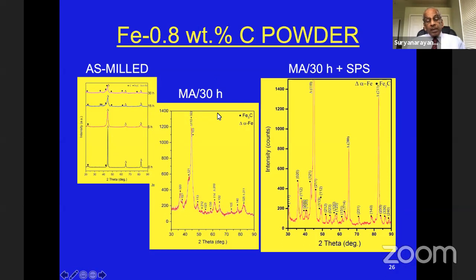And if you subject this powder milled for 30 hours to spark plasma sintering, as I indicated earlier, you can see the peaks are very, very sharp because there is an increase in grain size, and all the strain that was present in the milled powder is also released. Therefore, you can see very sharp and very high intensity peaks, and therefore you will be able to easily identify the phases, which turned out to be only alpha iron and Fe3C. This is what we expect even from the phase diagram of iron carbon.